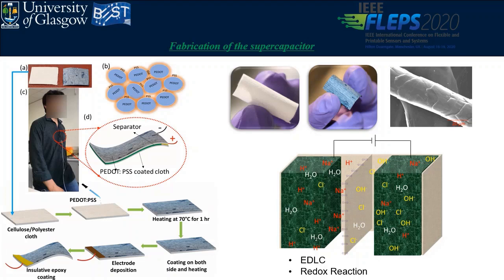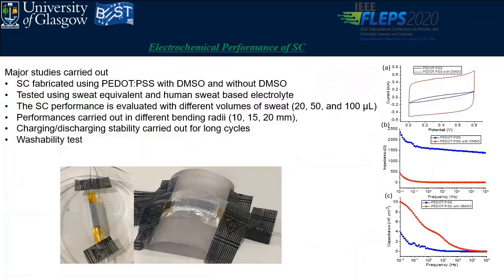I used cellulose polyester as a separator, and when we applied a potential, the positive or negative ions from the electrolyte separated depending on the polarity of the electrode. And here, due to the conductivity of the polymer, two reactions happen. One is electrochemical double layer formation, and another is a redox reaction in the conjugated polymer, because PEDOT:PSS has some complex electrochemical reactions. And we carried out the major studies, initially with PEDOT:PSS alone, looking at the supercapacitor performance with a sweat-equivalent electrolyte.